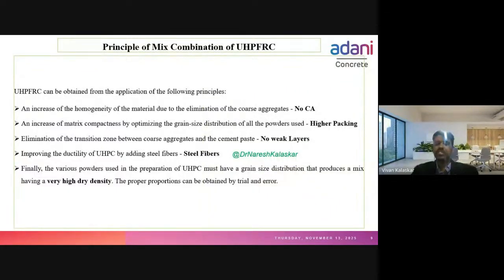The main principle of this UHPC is that there will be no coarse aggregate in the mix. Usually we add 20 mm and 10 mm aggregate in normal concrete. But in the Indian UHPC which we have designed, in this mix we have used 2.36 mm as the maximum size of aggregate. The second principle is higher packing density and no weak layers, and steel fibers, which, as I told you, improve ductility in UHPC and reduce the shrinkage. And these are the main mixed combinations of UHPC.